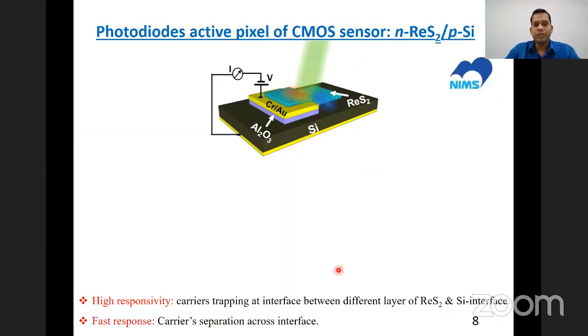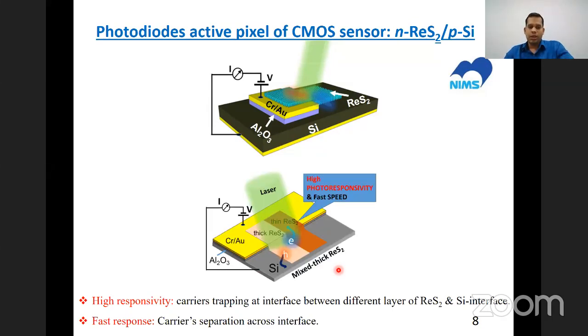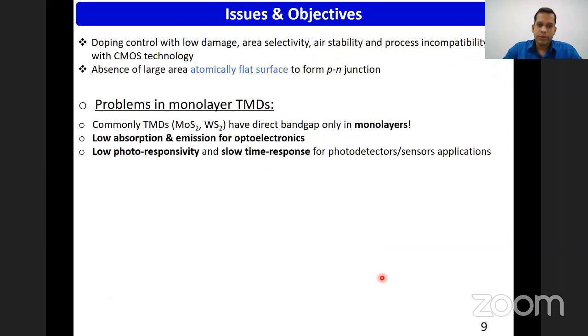So I'll start with these photodiodes. It is very interesting that what we observe is that if the thickness of ReS2 combines thin and thick, then that can actually show high responsivity for sensing applications, and it also shows a fast response in the device. Of course, there are various issues in industry in terms of doping control, area selectivity, stability, and also getting an atomically flat surface.